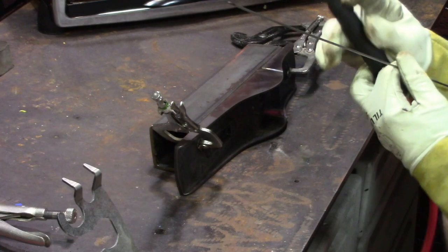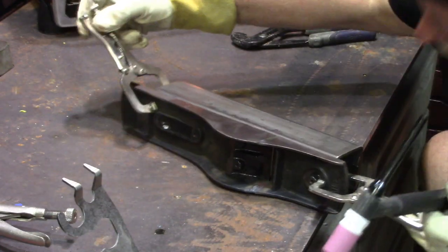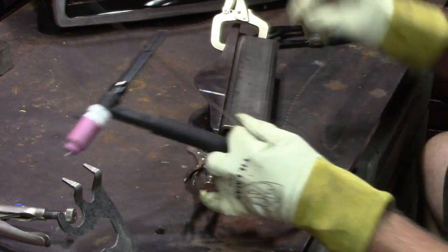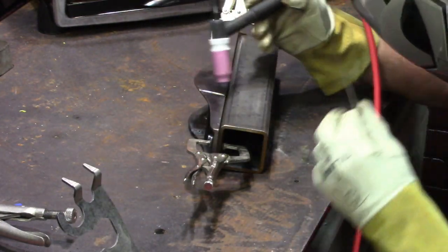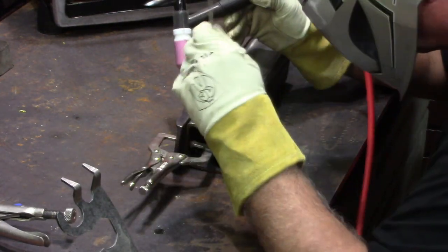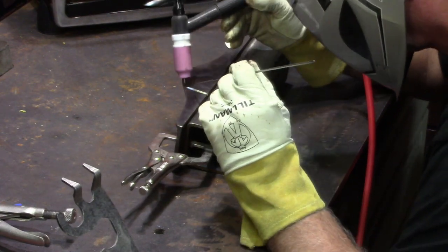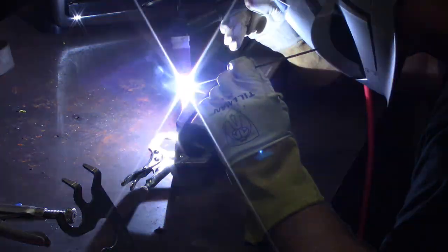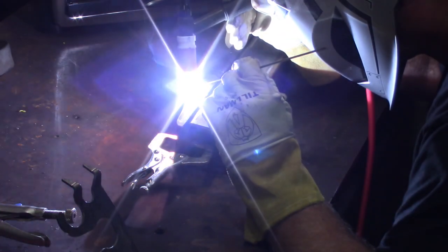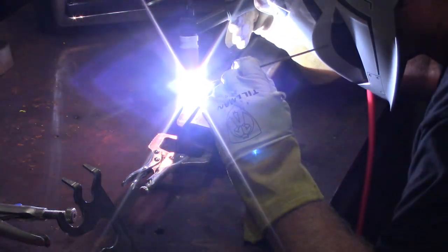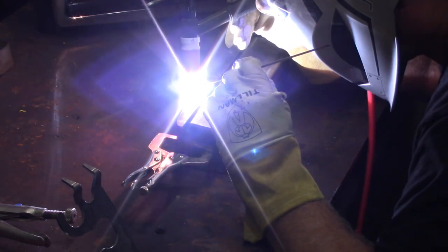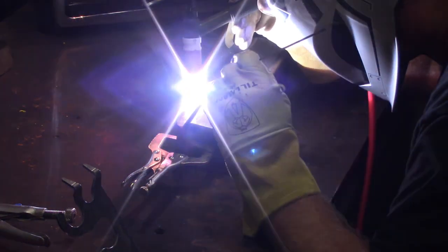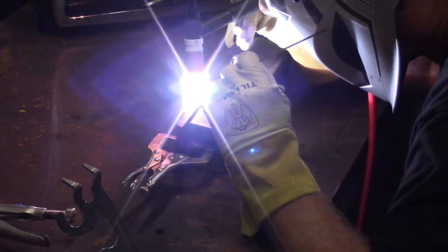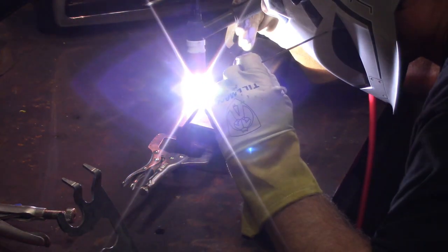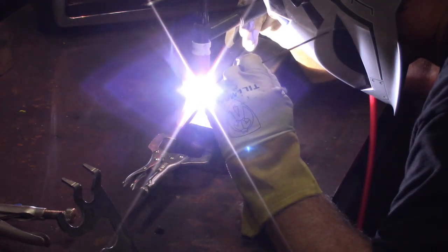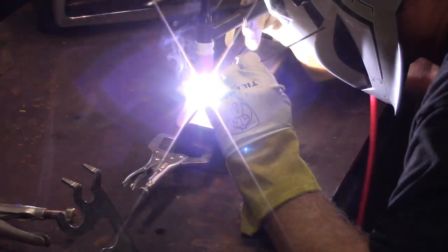Kind of an FYI, I've got my welder set for 105 amps, straight DC, and it's just about the right temperature. I've got enough heat for the casting without the risk of blowing through it. And I'm using a pedal to modulate it. But you can see how much heat I'm putting into that cast iron right there. And right now, remember, the ends of that cast iron are cooling off. Hopefully that piece of steel will supply enough additional thermal mass that it will keep it hot long enough that it won't fracture on me.